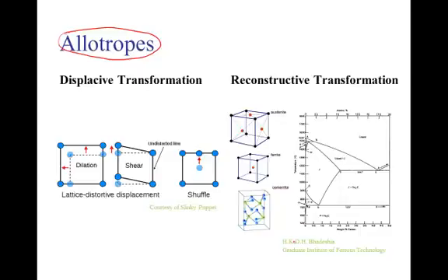So I have the phase diagram for steel here, our steels and cast irons in this system. We have mixtures of iron on the left and carbon far to the right there. And the vertical axis is temperature. So as we go to the top of the chart, we're going to higher temperatures. And at room temperature, we have one crystal phase, we call the alpha phase or ferrite. And actually there's two crystal phases, ferrite and cementite, mixed together with each other.